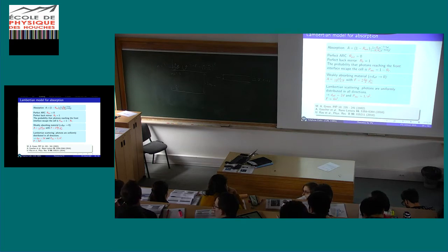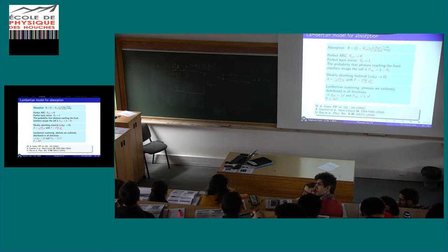That's because the 4n² is the average light path. One example would be a wafer where you need an anti-reflective coating to avoid the reflection, but it's still flat. So if it's flat, you're getting only light in, light out. That's only a factor 2 with the reflection. Then you make a little tiny scratch on that wafer. That already is 4n².